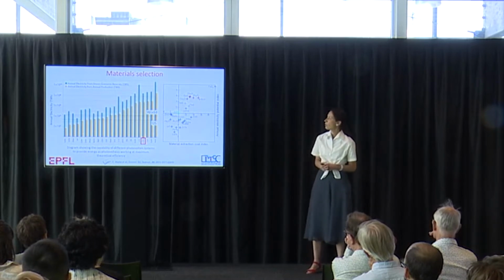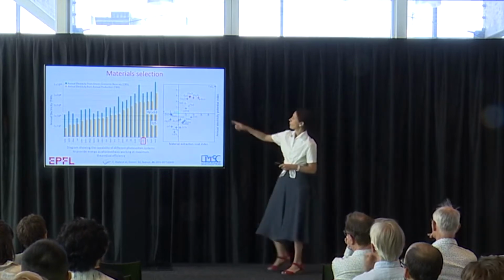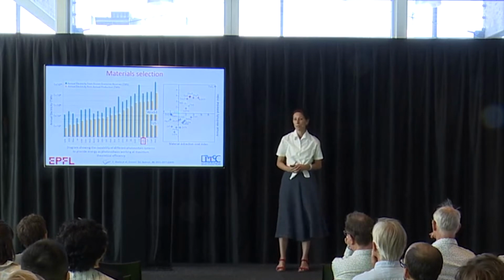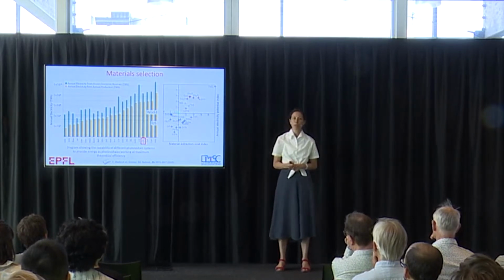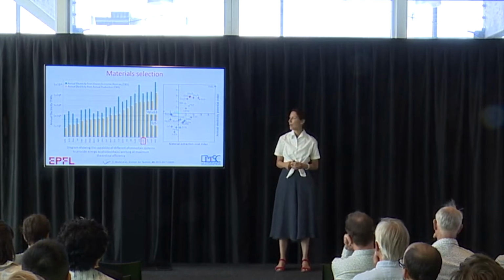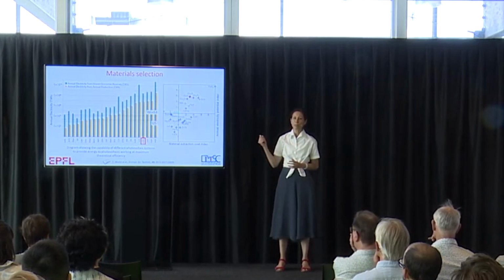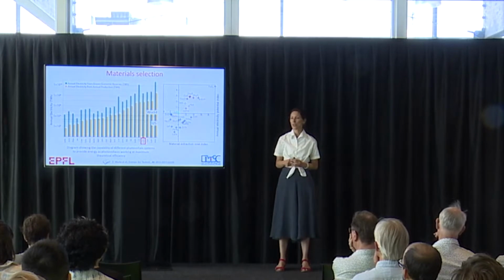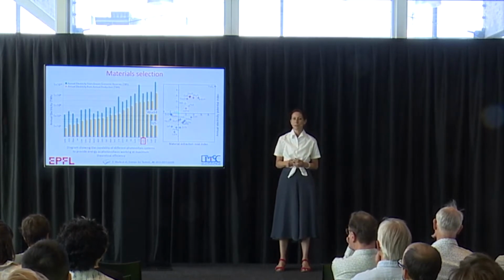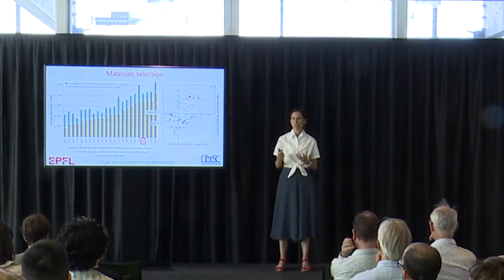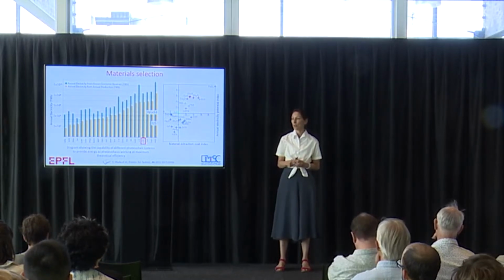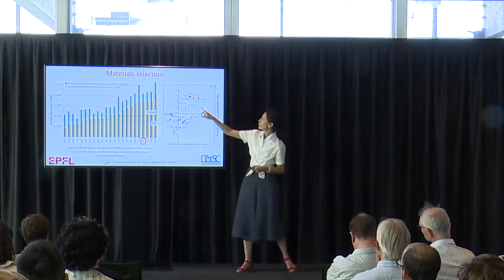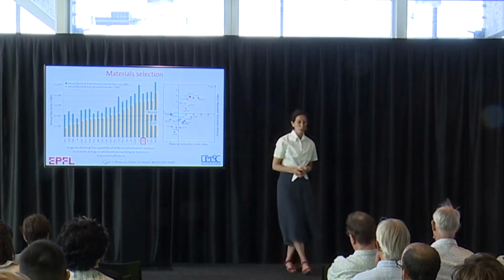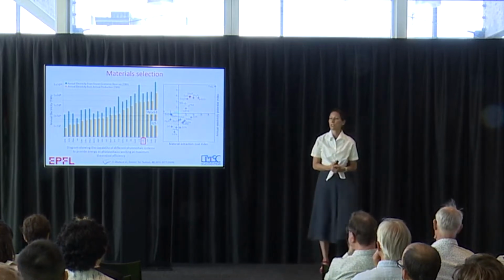So if you do this and you look at the potential, you have iron sulfide that would be the best one. Everybody would like to have a device on iron because there's so much iron in the Earth's crust. I think all devices that use iron, the efficiency is very, very low, and it's probably due to the fact that iron likes oxygen a lot, tends to oxidize a lot, so this creates defects. So this is probably one of the things. So then we went to zinc phosphide, which is here. It's also a new material. There have been some works in the past.